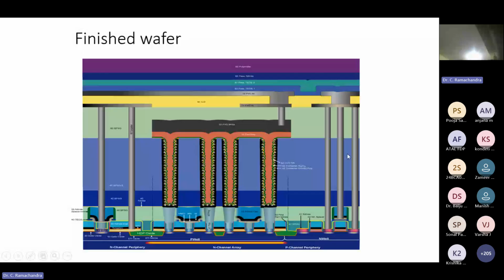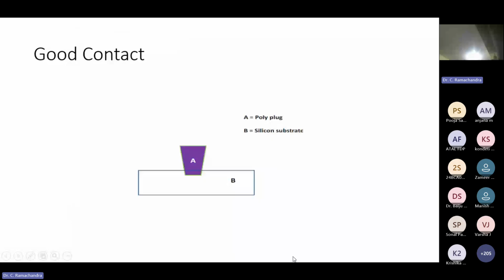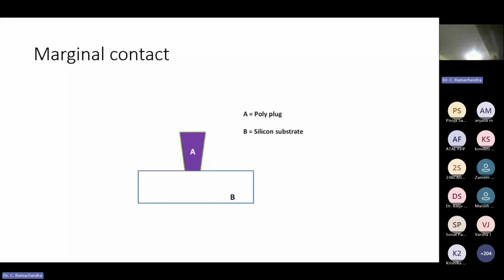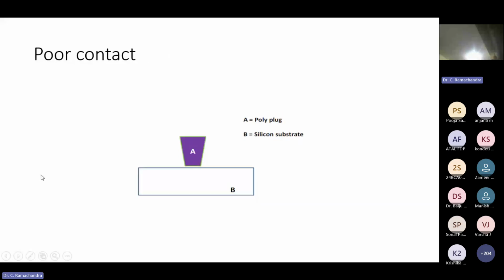So what is the meaning of insufficient buried contact? This is my polyplug and this is my silicon substrate. To have a sufficiently good electrical contact, this polyplug should penetrate 2 nanometers so that it provides electrical contact. This is the example of a good contact. But if I go to that one, it is a marginal contact. It is working, but it can create problems. And sometimes it can have a poor contact. It is some thin layer of oxide, still some partial contact. It is not acceptable. This kind of problem was unnoticed until we manufactured.